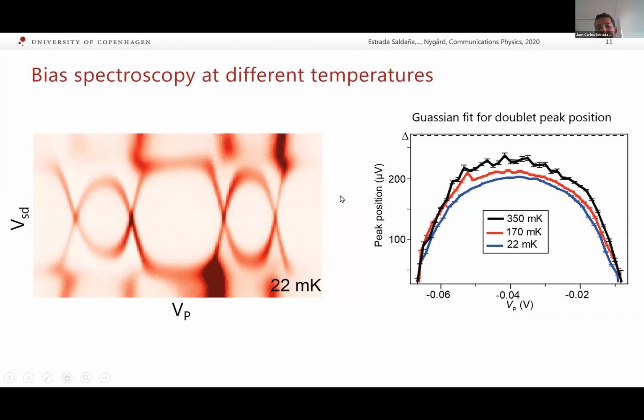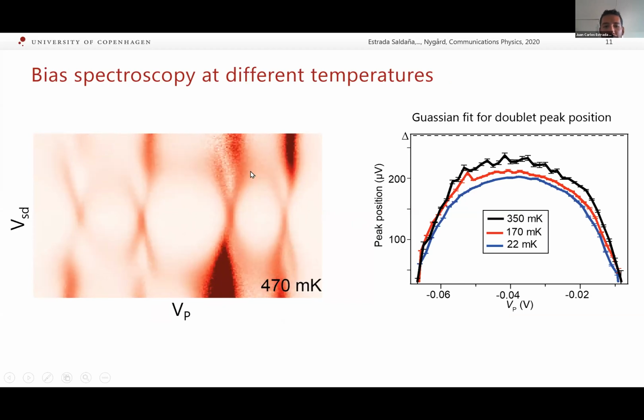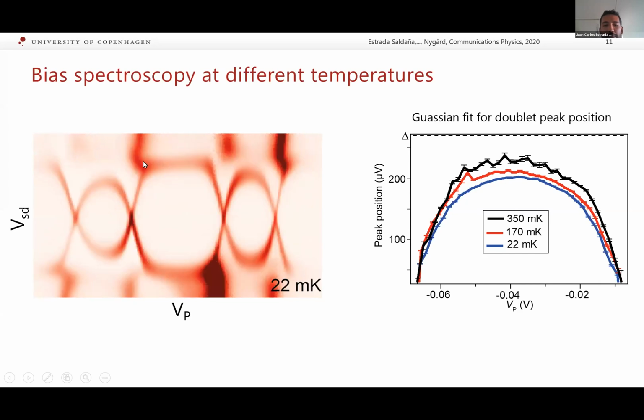Next, we go to the actual novelty of our experiment, which is the temperature dependence. So let's see how this map of differential conductance versus source-drain bias and plunger gate voltage evolves in temperature. This we can see in the left animation here. And what we see is, as we increase the temperature, the small loops, which are our doublet ground state, grow and they fade away towards the gap. And the big loops of singlet ground state, they just fade away, they don't shift. So these loops grow and these don't shift.